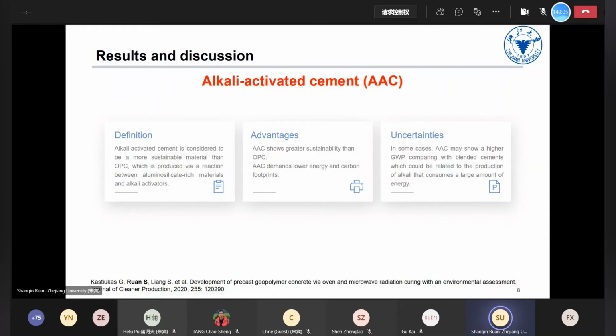Alkali-activated cement is considered to be a more sustainable material than OPC, and it is produced by a reaction between aluminosilicate-rich materials and alkaline activators. In terms of its advantages, AAC shows greater sustainability than OPC, and demands lower energy and carbon footprints. However, there are some uncertainties. In some cases, AAC may show a higher global warming potential compared with blended cements, which could be related to the production of alkali that consumes a large amount of energy.